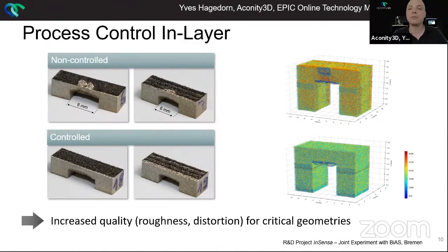On the right hand side, we see the sensor signal. We see a little bridge, which in additive is not easy to manufacture, because you would want to support such structures. If you don't do that, you can get those defects as you see here. On the top, we see our non-control process, also the sensor signal. You actually see the defects. And what we have done is we applied an inline process control to that. Once we've done that, we see the quality of our part is tremendously increased.